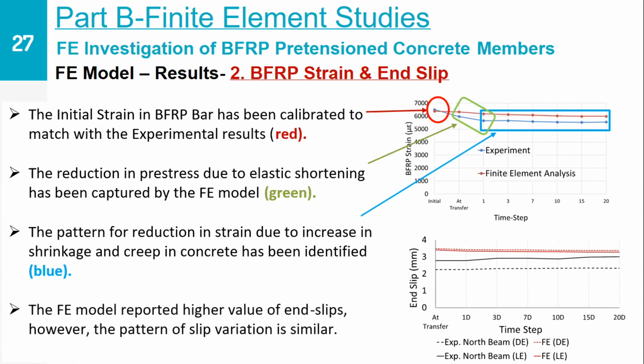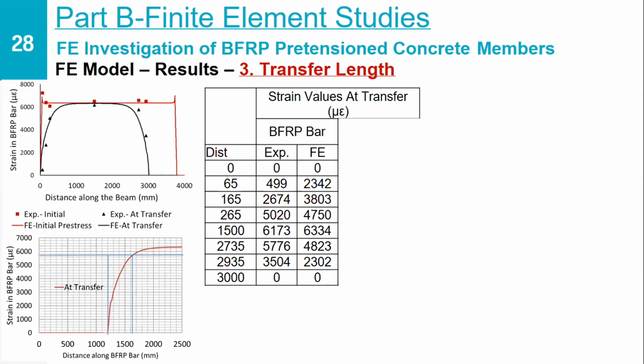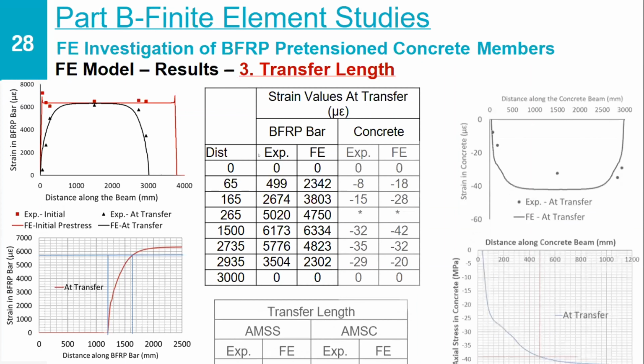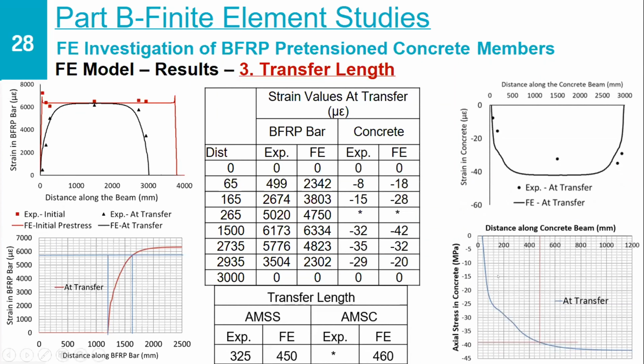And also, as I said, the FE model reported higher end slips. However, the pattern of the slip that has been obtained is similar and matches the experimental results. Coming to the transfer length that has been obtained, the transfer length has been obtained using the strain gauges on the BFRP bar as well as the strain gauges on the concrete. So we can see here that the transfer length obtained from the strain profile matches well with the experimental results. And these are the strain profiles obtained from the concrete and the transfer length.